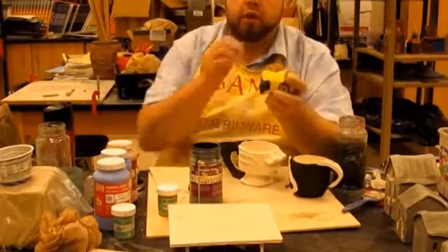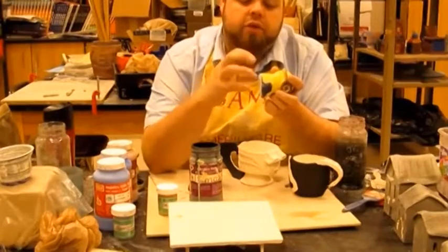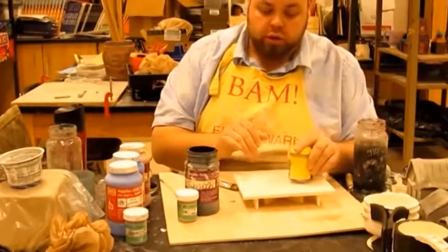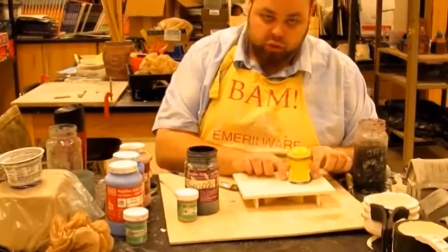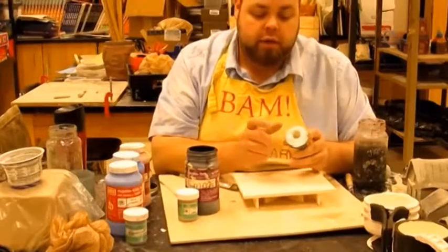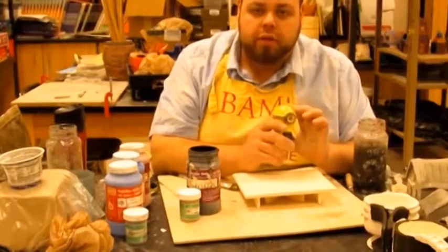When applying glaze, don't go all the way down to the foot or the rim at the bottom — give yourself a little space. If the glaze is too thick and runs down past the foot, it will weld to the kiln shelf and I'll have to smash your piece off. The kiln shelf has kiln wash to protect it, but thick glaze will melt and attach to the shelf. As a precaution, always sponge the bottom rim clean to make sure there's no glaze on the foot.